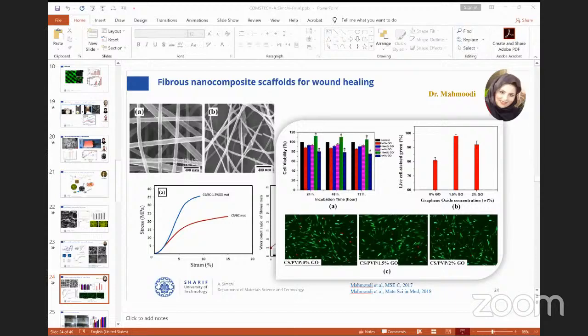We have shown that the addition of graphene oxide increases the mechanical properties of fibrous materials and also improves the wetting properties, hydrophilicity, which is important for wound healing applications. And then we made a lot of efforts on cell viability, on live/dead assay, and so on. All examinations show the materials can be used for wound healing applications. However, the main problem was the mechanical properties and elasticity, because the elastic properties are very important, and also the mechanical properties have to be close to the skin.